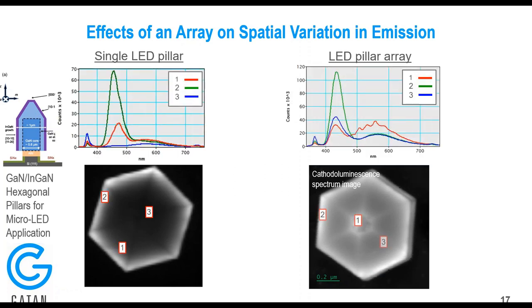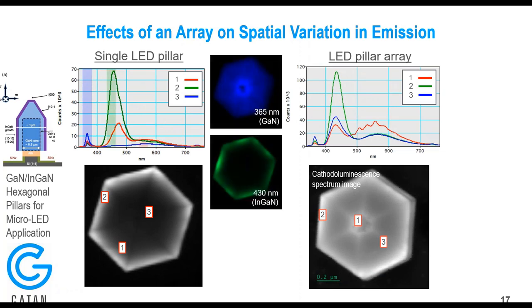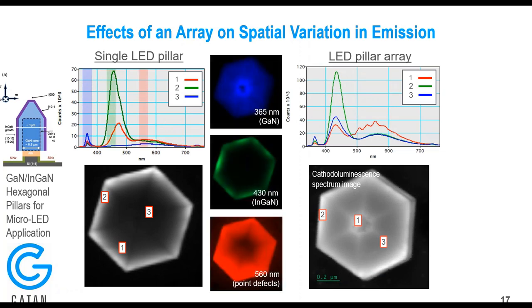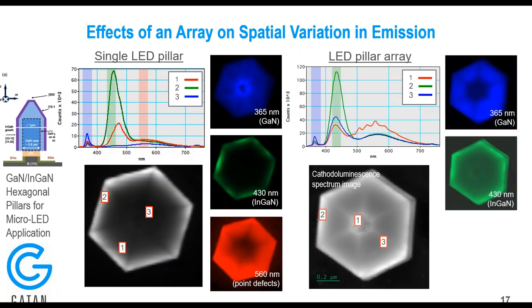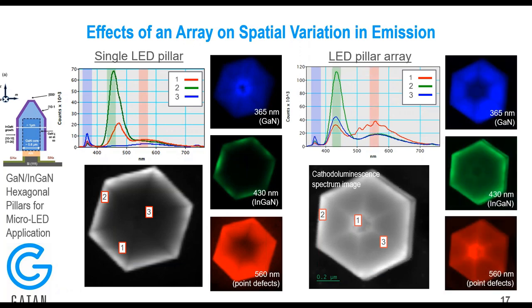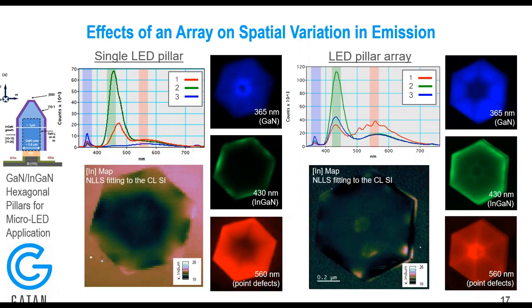And so once again, we can extract spectra from characteristic points throughout the sample, look at the colorized bands that have been acquired, and determine the differences. And it helps to put them side by side so you can see what the differences are between the array and the single pillar by itself. And again, with the nonlinear least squares fitting method, you can see the effective concentration of the indium across the hex pillar surface, and it's been adjusted based on the effects of the array.